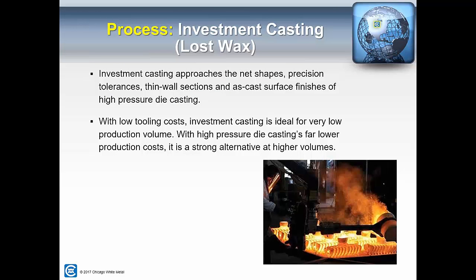Investment casting, or lost wax casting, is another competing casting process. It does a pretty good job of creating surface finishes that are almost as good as high pressure die casting. It can do some net shapes. Its advantage is it can do undercuts and things like that, because the mold is removed and it's not made of hardened steel like die casting. So there's an advantage there if you have undercuts or hollow shapes and so on. But again, lower investment but higher piece price. The cycle times are longer. There are certainly advantages to going with high pressure die casting when the volume increases.